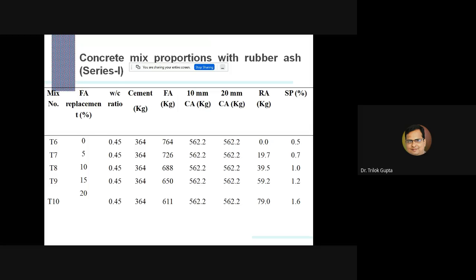Now, mix details. In that case, we cast two series. In series one, we kept the water cement ratio at 0.45, and in the second series, the water cement ratio was also 0.45. In the first series, we replaced with rubber ash in increments of 5% up to 20%. The cement content was 364, with fine aggregates and coarse aggregates, and we used superplasticizer to maintain the workability or compaction factor near 0.9.